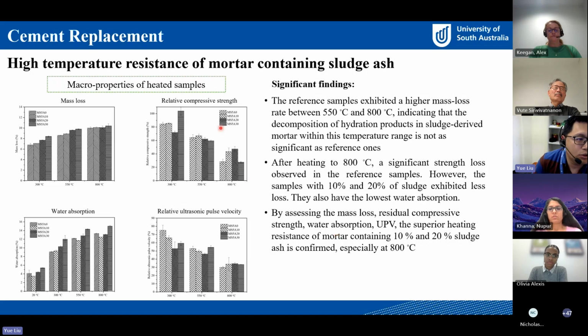For example, for the residual compressive strength, after heating to 800 degrees, a significant strength loss can be found in the reference sample. The strength reduced to around 28%, but the samples with 10% and 20% sludge retained 43% and 47% of their original strength respectively.